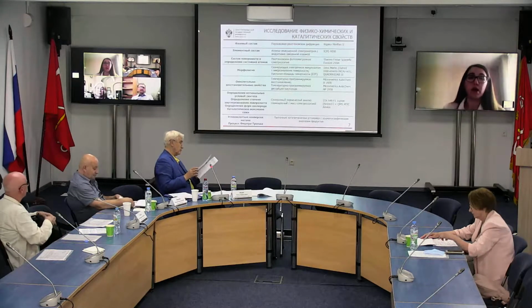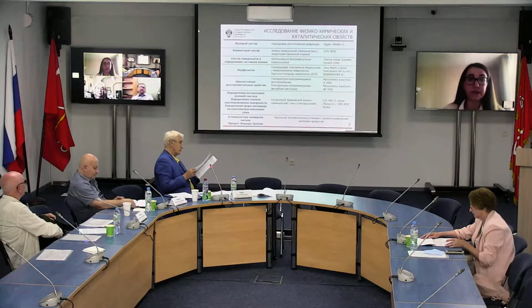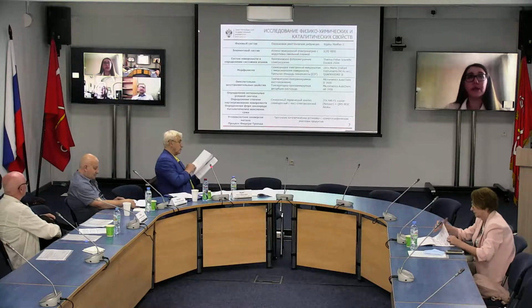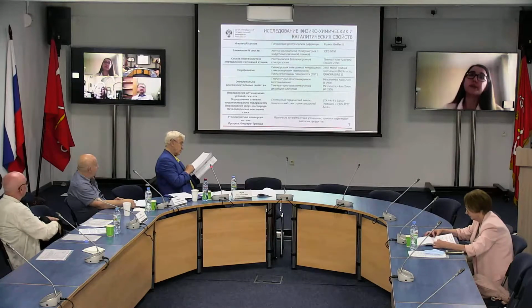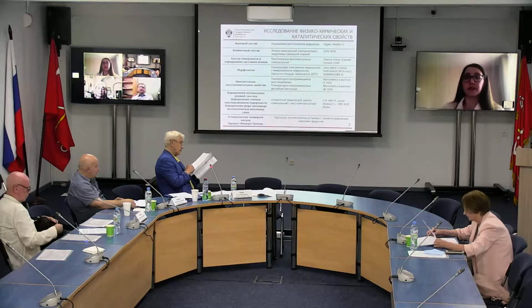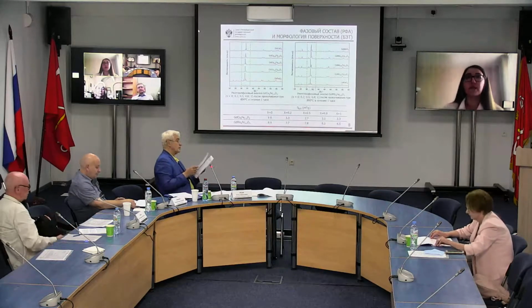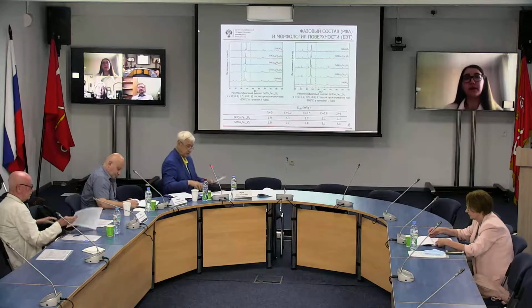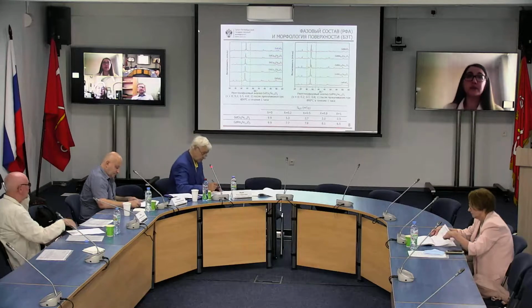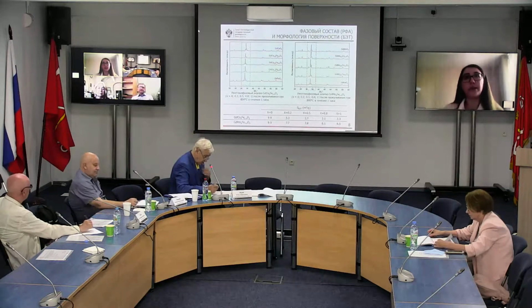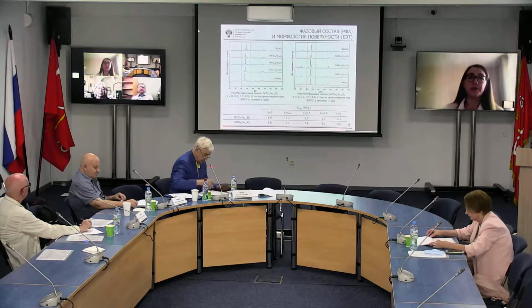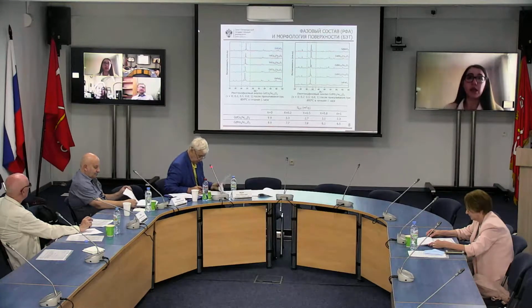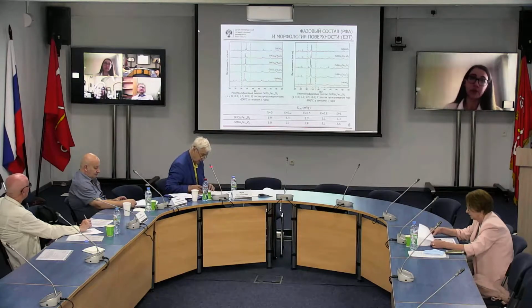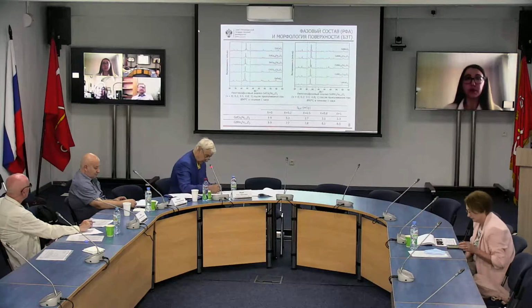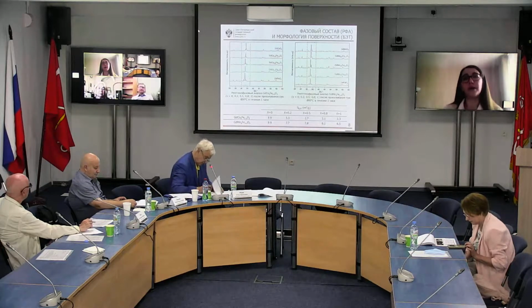Simultaneous thermal analysis combined with mass spectrometry is used to estimate the carbonization level, and catalytic characteristics are studied in the processes of Fischer-Tropsch and dry reforming of methane. The results of the study of phase content demonstrated that the devised method allows us to get single-phase oxides, and all diffraction peaks are associated with ferrite, cobaltite, and manganite of gadolinium and their solid solutions. The specific surface area was assessed using the BET method. Ferrite of gadolinium has the highest value, and other complex oxides demonstrate rather similar results. Relatively low values are explained by the heating temperature.